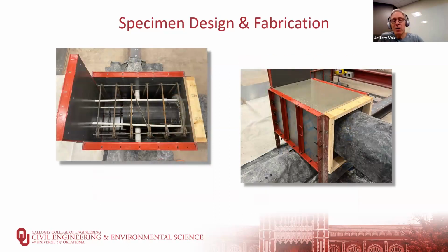Now, unfortunately, we only have a 5-ton overhead crane in our lab. And if we were to cast the loading stub on top of our column, they would weigh more than 10,000 pounds and we wouldn't be able to move them around the lab. So we actually had to tip the columns over, move them into the test frame, anchor them to the test frame, and then fabricate the reinforcing cage and the formwork to install the loading stub.